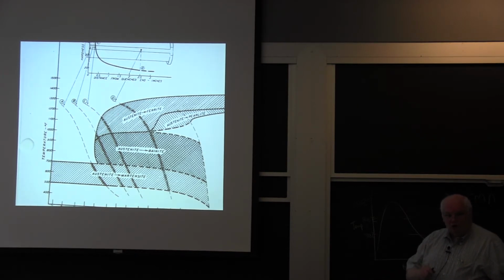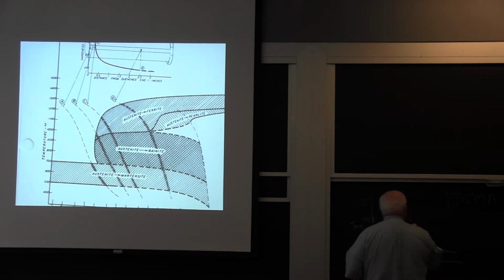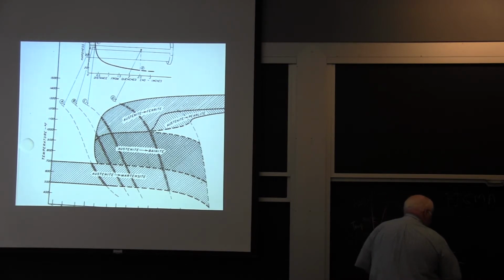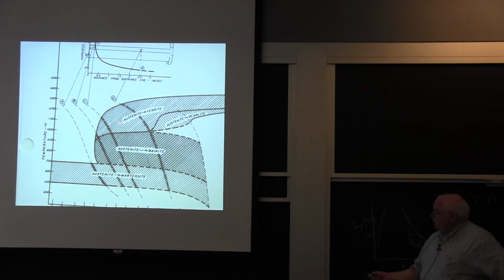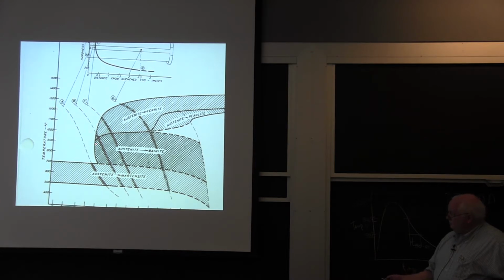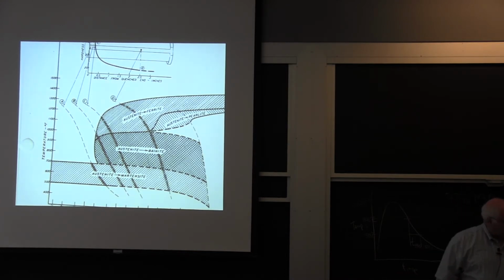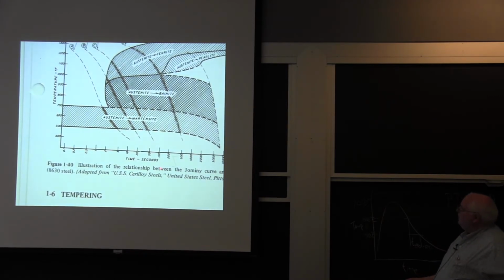And you're right, welders like to talk about the time to cooling, delta T is T 800, 500 in the welding literature. And that's because that's how long it takes for you to get through this transformation region. And if it's a simple carbon steel, you got to get through there in less than a second. Do they put time scales on here? This one is actually slightly alloyed. It's 8630 steel. So slightly alloyed steel, if this was a carbon steel, you'd have to get through there in half a second to not get martensite.